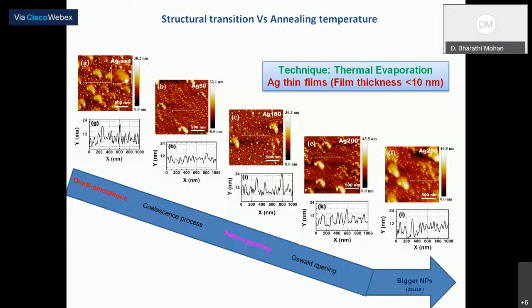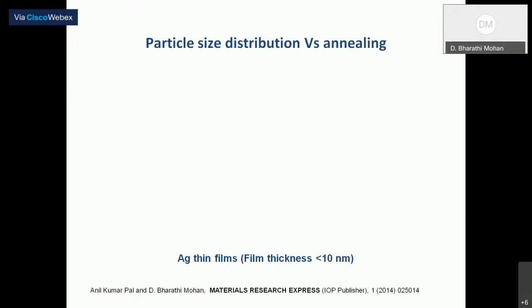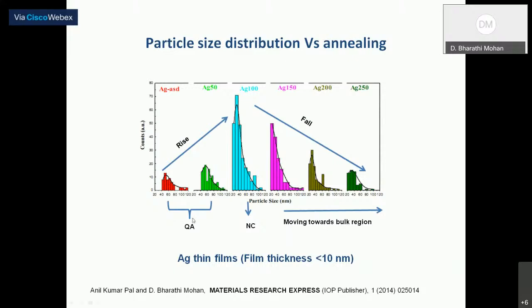And further, if you anneal the film at 250 degrees Celsius, the nanocrystalline state is converted into bulk state, where you can see the formation of bigger nanoparticles and agglomeration is dominant. So the entire process takes place through coalescence and Ostwald ripening. We have calculated the particle size distribution as a function of annealing. You can see very clearly when you go from the quasi-amorphous state to the bulk, as you increase the annealing temperature, the number density of the particles increases. At the same time, the particle size becomes very narrow. On the other hand, in the quasi-amorphous state or in the bulk state, the particle size is bigger and the particle number density is very small.